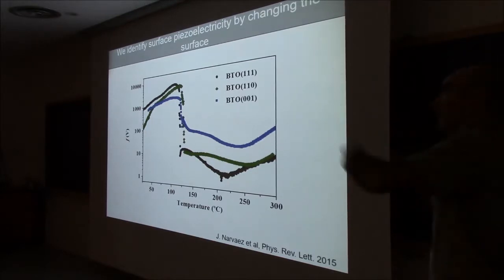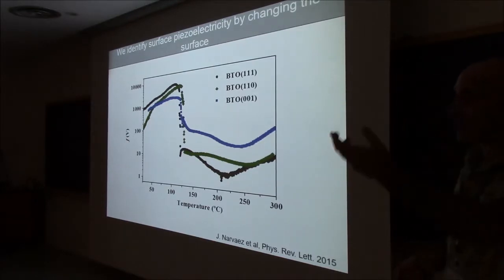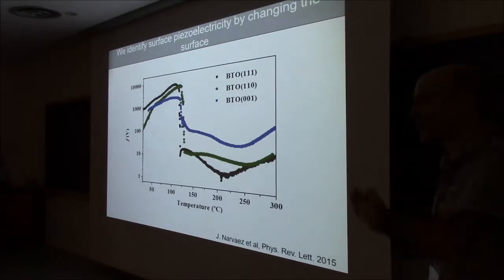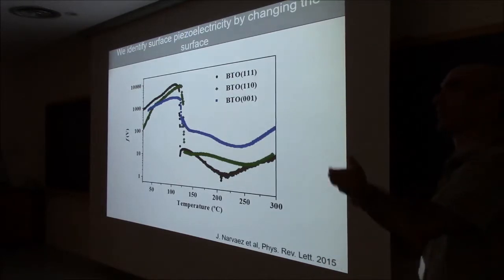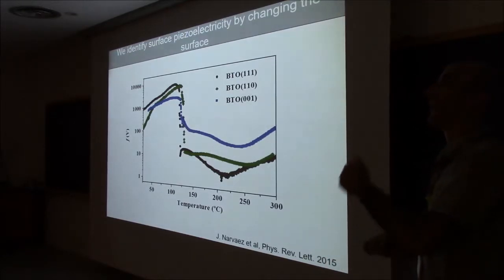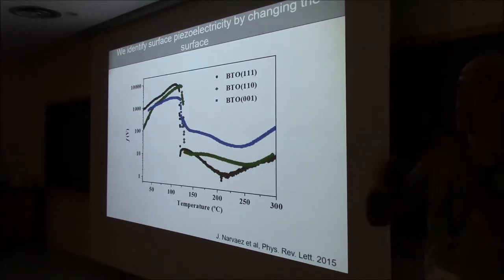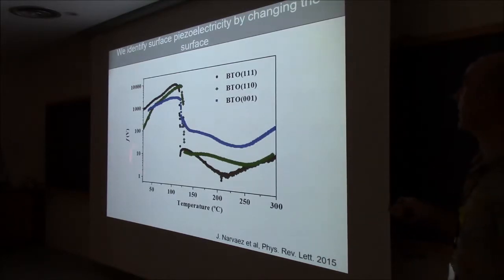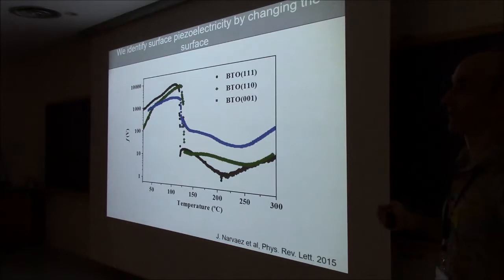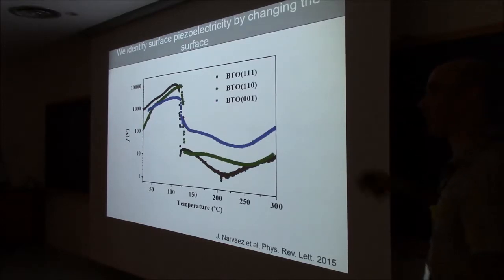Displacement current multiplied by the frequency is the charge, which divided by the area is the polarization, which divided by the strain gradient is the flexoelectric coefficient. And that, divided by the dielectric constant, which I measure separately, is the flexocoupling. Okay, so I don't measure directly voltage, I measure current.